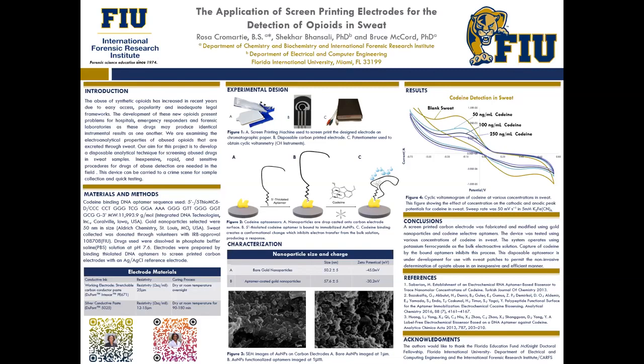So we're also able to see that the charge of the aptamer coated gold nanoparticle shows an increase in charge, which is shown under zeta potential. Because the aptamer is blocking the surface charge of the gold nanoparticles from the electrostatic potential. So as I showed you in the previous schematic design, the aptamer will block the ferrocyanide from creating electron transfer between the surface. So this coincides with what we see in part C.